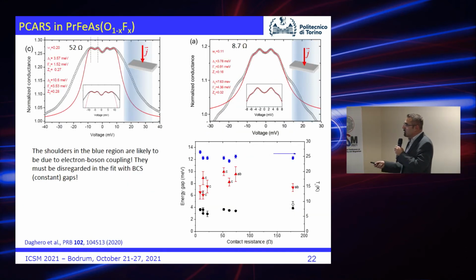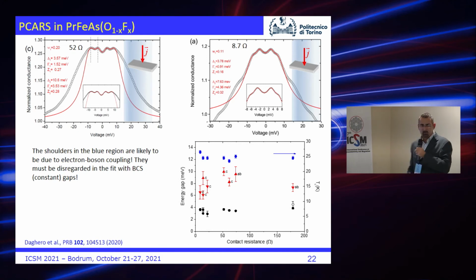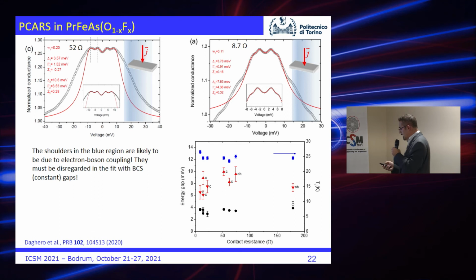These are other examples in which the 2 gaps are much more clear. You see one gap, the other gap, one gap and the other gap, and these are electron boson interaction structures. If you plot the gaps as a function of the resistance, you see that there is no clear tendency, and this is important because this tells us that we are very likely to be, at least at low temperature, in the spectroscopic regime. But if you look at the data, you see that the small gap is rather well defined. The large gap, not so well.